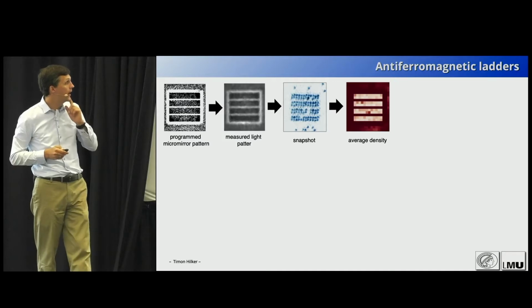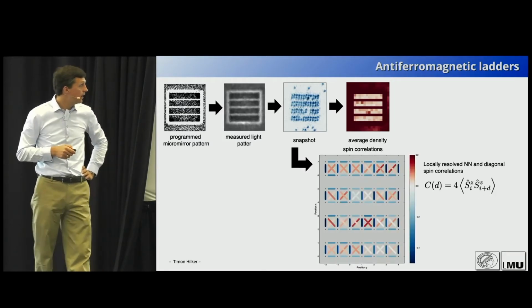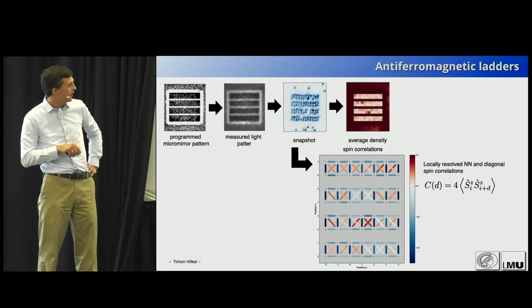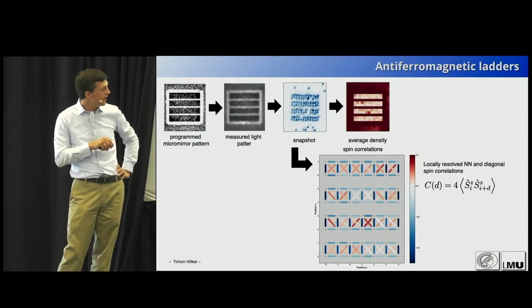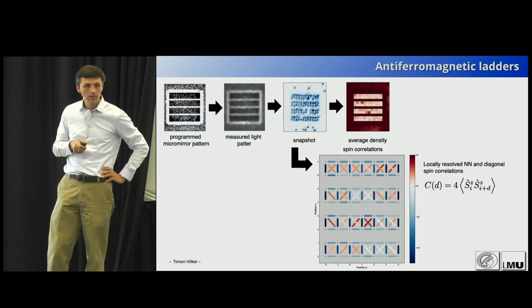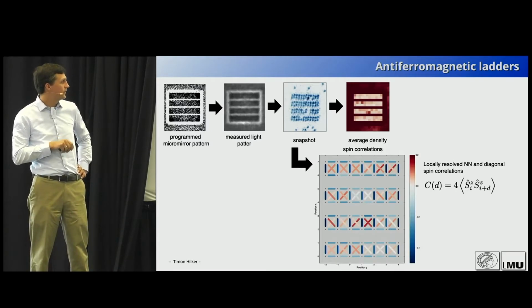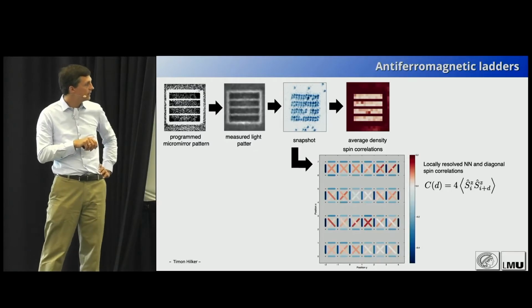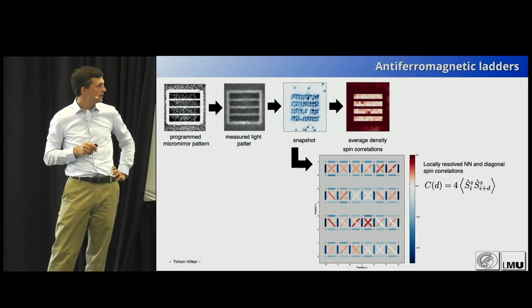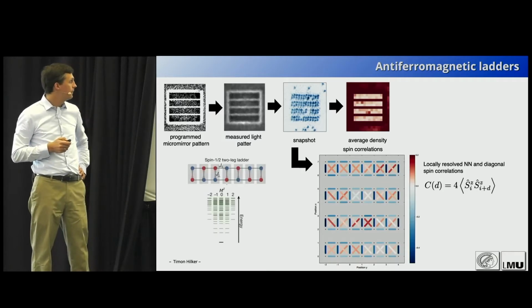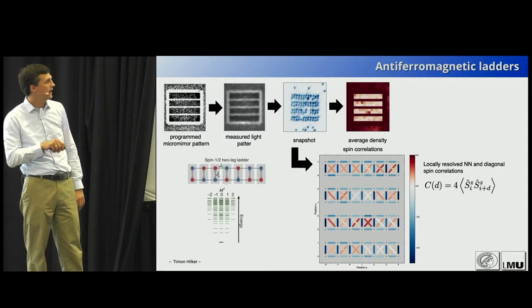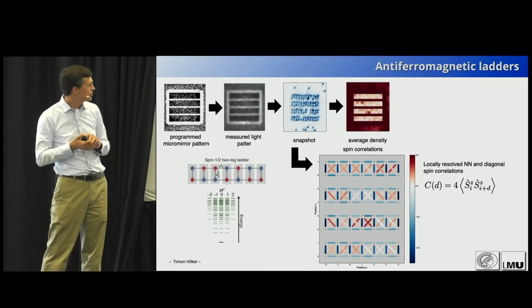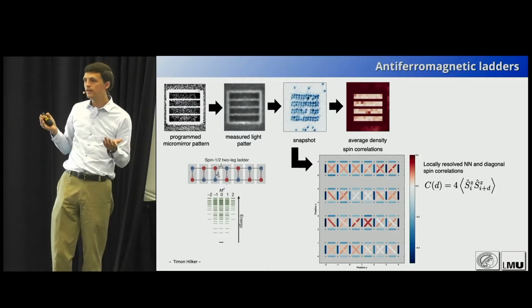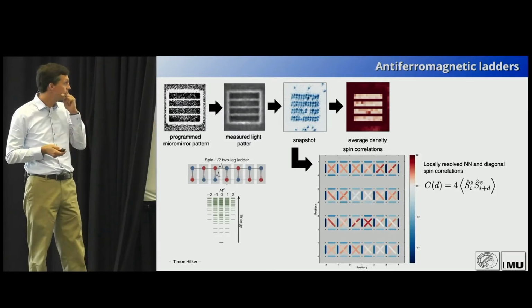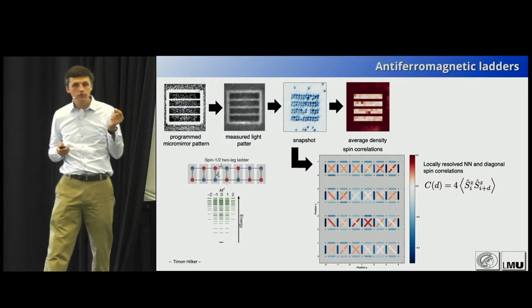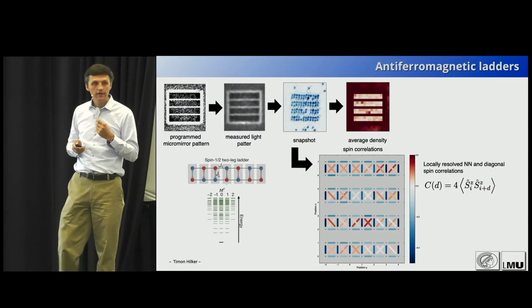So we made those ladders, and here you can see directly the analyzed spin correlations for nearest neighbors and diagonal ones, now spatially resolved over the system. One sees what one expects: antiferromagnetic nearest neighbor correlations and then ferromagnetic correlations along the diagonals. But of course, this system by itself, if I analyze it like this, there's nothing really topological about it. It actually just forms strong singlets, so that's a spin 0, and I just get a chain of spin 0s. But what one realizes here is basically the trivial partner of that topological Haldane phase.